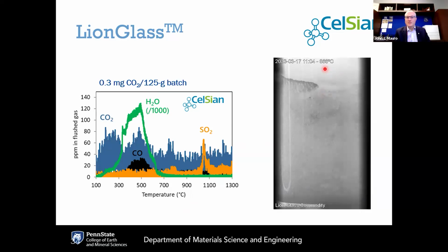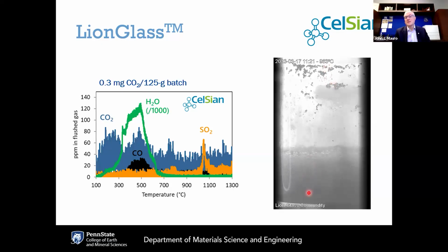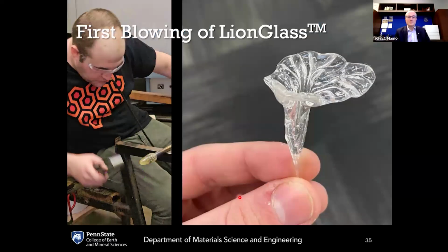Now, check out what's happening here. We are at 875 degrees C, and you've got really fast kinetics happening. You've got these SO2 blisters coming through from the fining agents. 900 degrees C in LionGlass looks a lot like 1400 or 1450 in soda lime. And as we get to 950 degrees C, everything's calmed down. So 950 is a lot like 1500. You get a nice homogeneous melt at about 500 degrees less in this particular case.